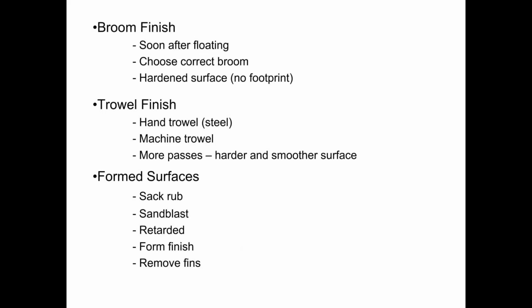Oftentimes a broom finish will be applied to a concrete surface that is going to have either vehicular traffic or foot traffic. The broom finish helps to ensure that there is adequate friction should the concrete surface be wet, so that a car can get traction and so that people don't slip when they're walking on that surface. One of the most common products that we see with a broom finish would be a pre-topped double T for a parking garage. Usually the broom finish is applied fairly soon after the floating operation.